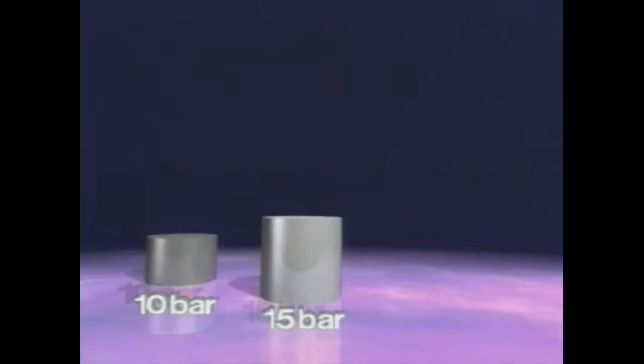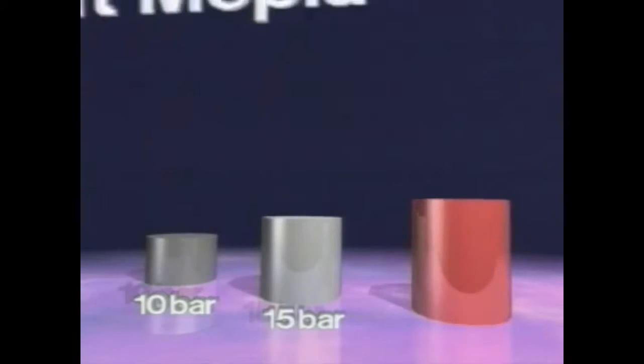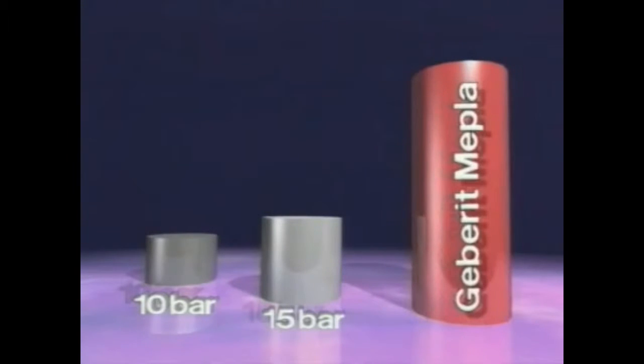The usual maximum pressure for a pipe system is 10 bar. The standard with a safety factor of 1.5 requires a test pressure of 15 bar. Geberit Mepla withstands internal pressure of over 40 bar, even after 50 years.